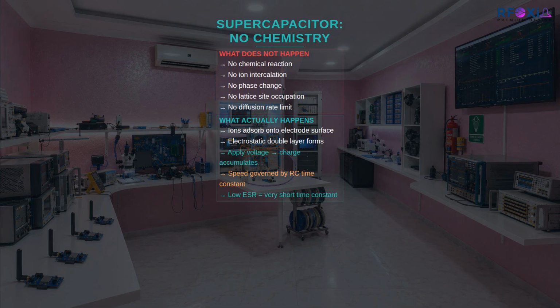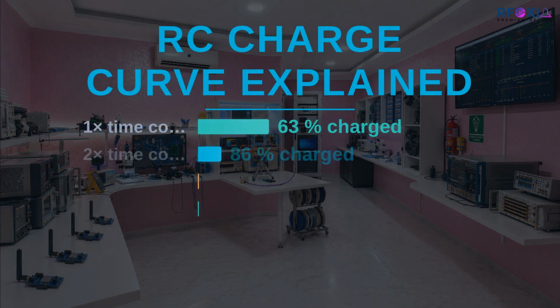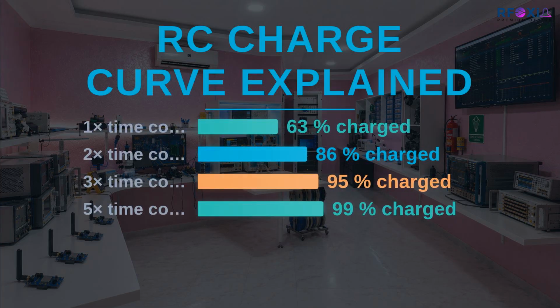This is why the charge curve of a supercapacitor looks the way it does. In a simple RC circuit, voltage across the capacitor rises exponentially toward the supply voltage. Theoretically, it reaches approximately 63% of full charge in one time constant, 86% in 2, 95% in 3. For a supercapacitor with a low equivalent series resistance, what engineers call ESR, and a high current source, that time constant can be very short, minutes, not hours.